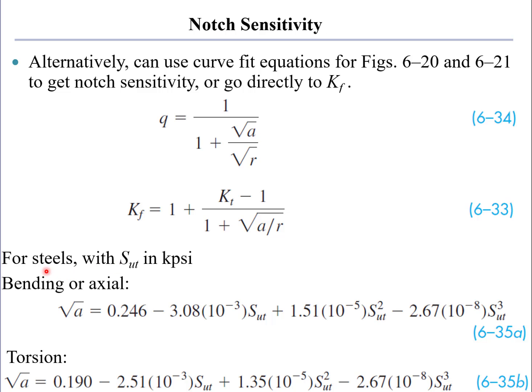For steels, and all that I'm talking about right now are steels, in bending, measuring the ultimate tensile strength in kpsi, we get that the Neuber length scale, square root of A, is given by equation 635. This equation gives you a length scale in dimensions of square root inches. The prefactors in front of the ultimate tensile strength have units that convert kpsi, kpsi squared, and so on into square root inches. So you can only calculate these length scales using ultimate tensile strengths in units of kpsi for equation 635.